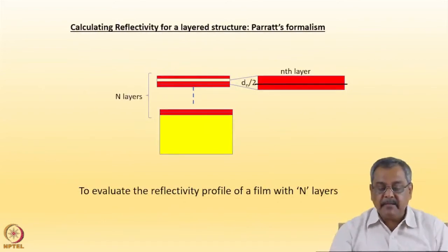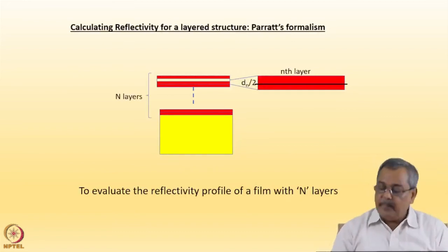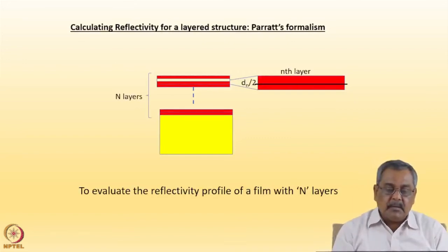But now the question is, how do we calculate the reflectivity, or how do we fit the reflectivity profile for a periodic bilayer, or periodic material, or a single film, or a bilayer, or any thin film structure that you want to study, or we have studied. So, I have talked to you about Rietveld fitting regarding crystalline structures. There, in Rietveld refinement, we start with the assumed structure of the crystalline solid, and then keep refining that till we come to a model which fits my experimental data. Then I discussed to you about liquid and amorphous solid. There also we start with a model structure, a three-dimensional model, and then we kept modifying it till we got a good fit with the experimental data.